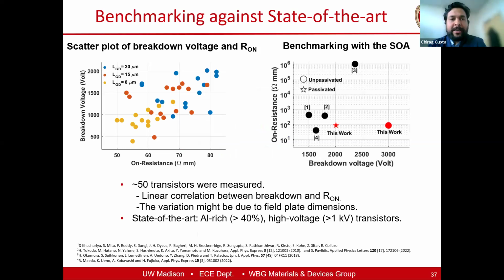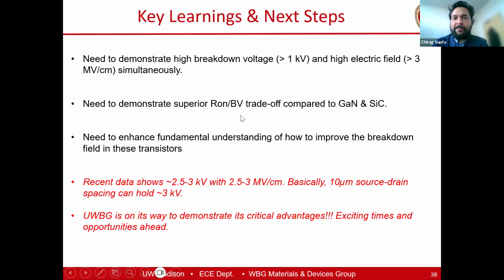So if we look at this work roughly, we see that with the gate-drain spacing, we are seeing a change in the breakdown voltage. When we compare our work with others, we are nominally where everyone else is. The unpassivated results, ideally, are not very useful because with unpassivated structures, current collapse is huge in these III-nitride transistors. So with passivation around 2 kilovolts, we have somewhere close to 80 ohm-millimeter. Very recently, we have improved those numbers significantly.